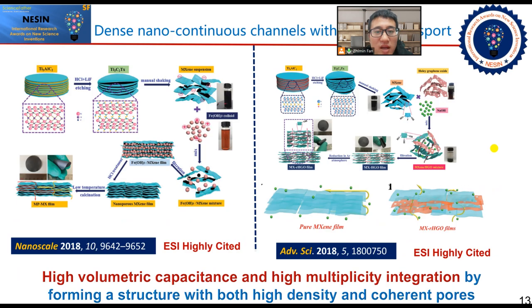To address these challenges, we constructed a series of dense nano-continuous channels with fast ion transport by using electrostatic self-assembly to introduce iron hydroxide nanoparticles into the MXene layers and embedding porous graphene into the modified MXene layers. A structure with both high density and coherent pores is formed to achieve an integrated electrode material design with high volumetric capacitance and high density.